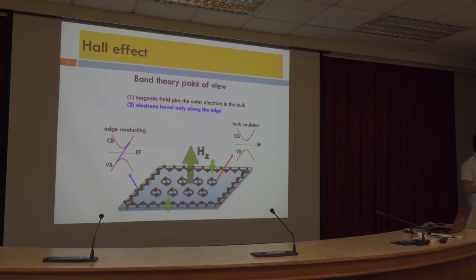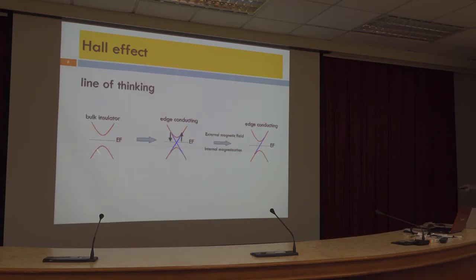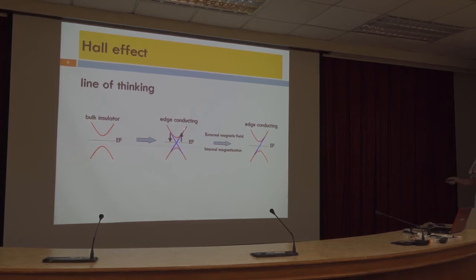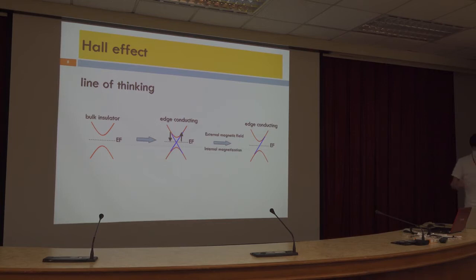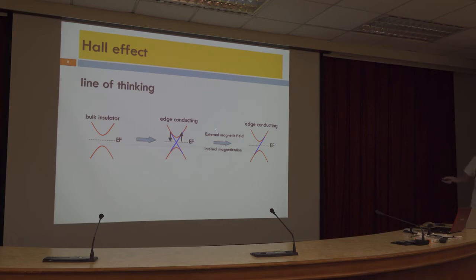This picture is very simple. How do we realize the quantum Hall Effect in real materials? Here I provide a possible way. In general, for a topological insulator, the edge band is occupied by an even number of electrons — there are two edge channels in the gap: one spin-down and another spin-up. Now, if we apply an external magnetic field or an internal magnetic field, one of the spin channels will be removed. There is only one edge channel left and the quantum Hall Effect is realized. But the remaining question is: what kind of material possesses this band structure?